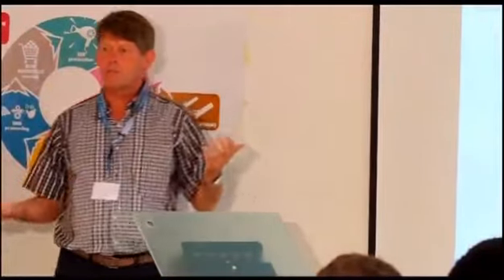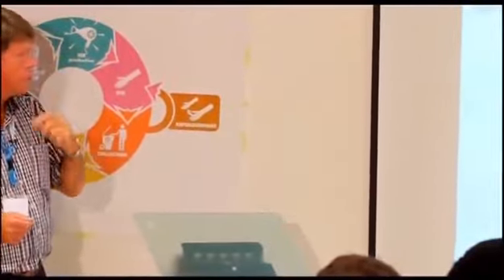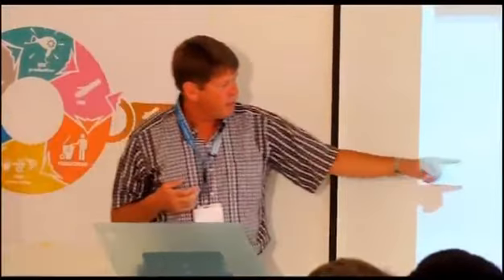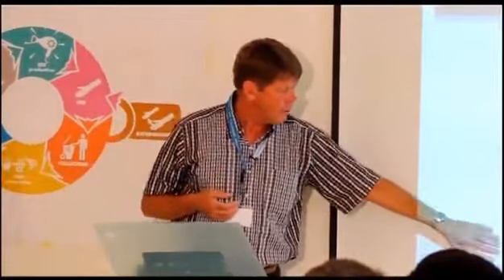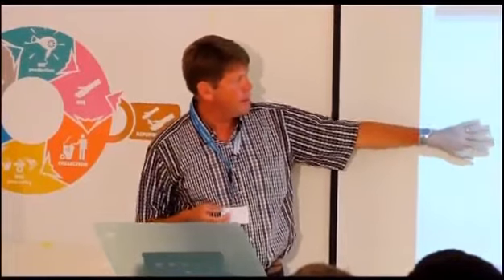And if you look at the composition of this material, that's what I wanted to come to, you have this pie chart, and it shows that for the small domestic appliances and ICT, about 60% is what we call target plastics. Target plastics are those that we produce. That is high impact polystyrene, ABS, and polypropylene. And then you have all sorts of contaminants. Contaminants like HIPS with flame retardants, which we need to separate. ABS with flame retardants, which we need to separate. PPO, PC/ABS, PC, PE, POM, PVC, rubber, wood, and also a little bit of metal. That's the typical mix that we get in our factory if you take the average over a long period of time.